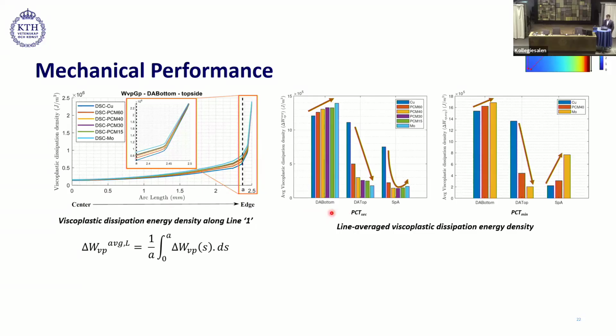First, that DA bottom solder layer, which is underneath the die, exhibited the highest dissipation density, both during PCT-SAC and PCT-min. And this dissipation density also increases with increase in percentage of molybdenum. However, in DA top solder layer, the trend reverses. So the dissipation energy density reduces with increase in percentage of molybdenum. In the spacer attached layer, we didn't see any specific trend. In PCT-SAC, we see that it first decreases and then increases. However, in PCT-min, we see that it increases.